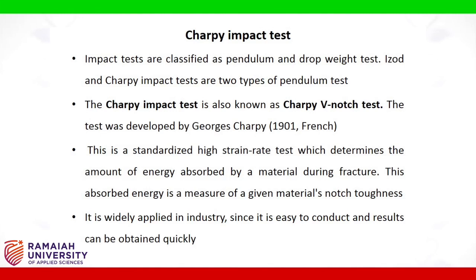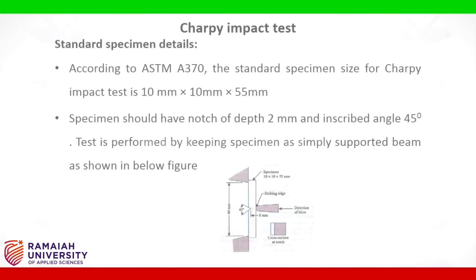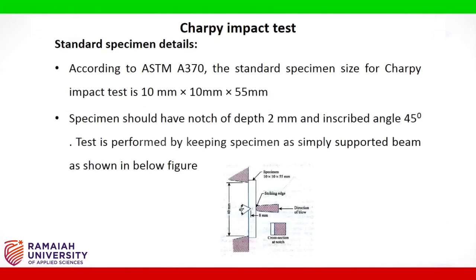The Charpy impact test is widely applied in industry since it is easy to conduct and results can be obtained quickly. Standard specimen details are per ASTM A370. The standard specimen size is 10 mm by 10 mm by 55 mm. The specimen should have a notch of depth 2 mm and inscribed angle of 45 degrees.